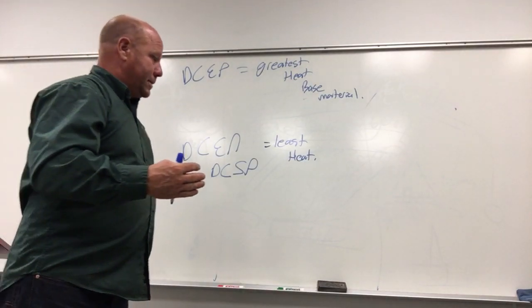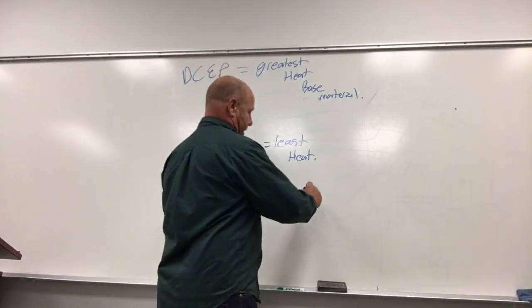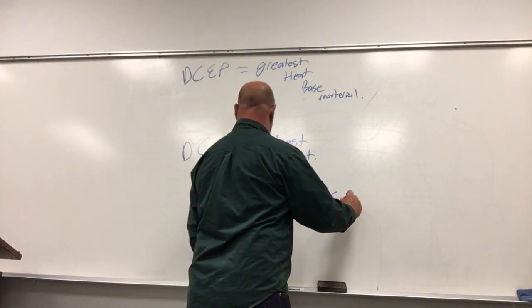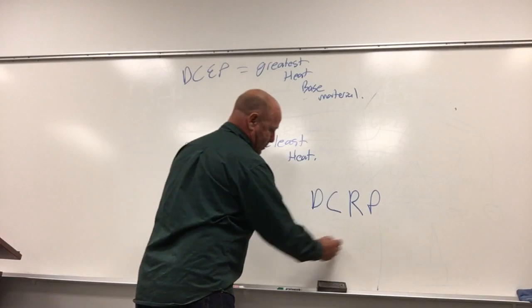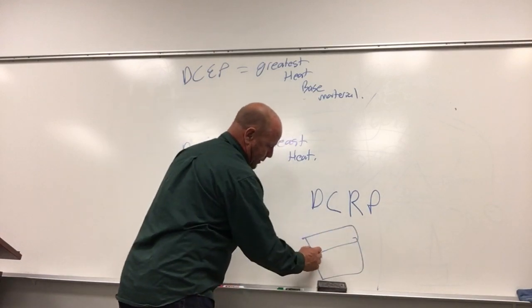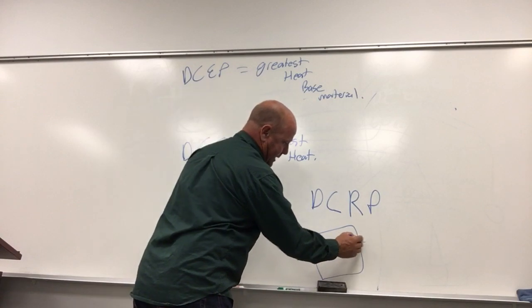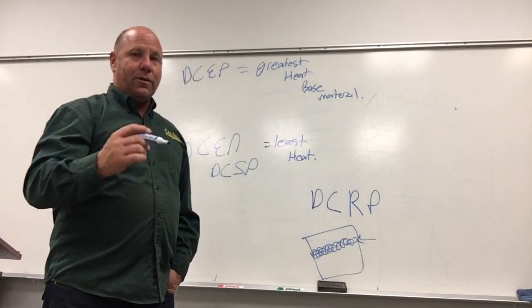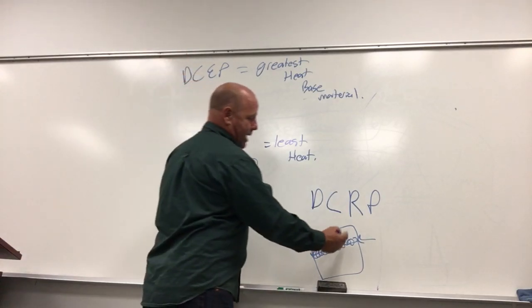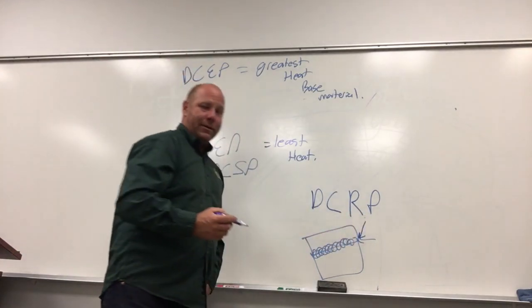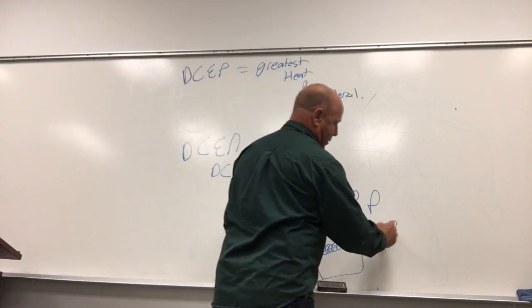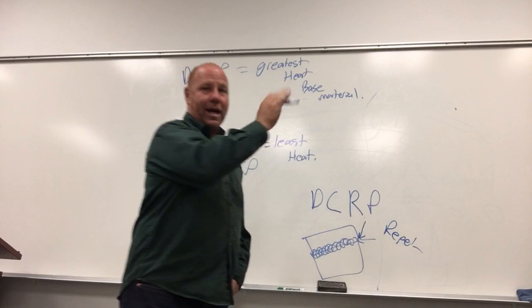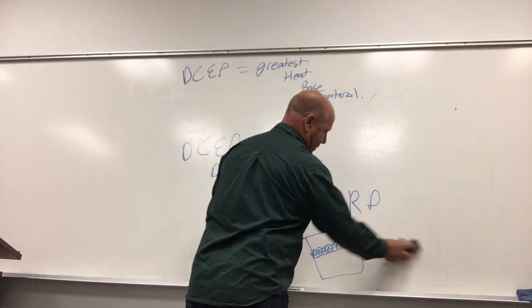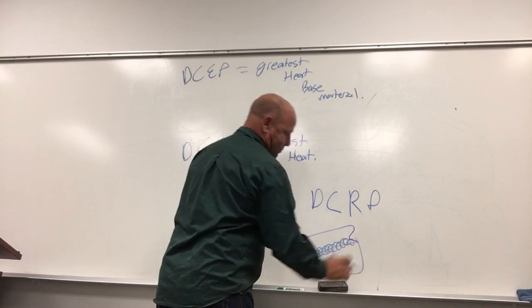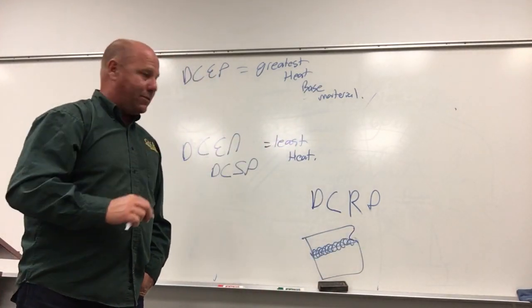Sometimes when you're welding with the DC process, actually every time, let's say you're doing a couple of plates and you're doing DC reverse polarity. Remember that's the same as electrode positive. You have two plates and you weld across. By the time you start reaching this end, you have magnetically charged these plates, and rather than attract this little ball into the puddle like we discussed before, you start to repel that ball. This ball goes flying out of the puddle over and over again. You actually repel it off, so that at the end of the plate, you end up with like a little divot like that, a little hole. Your weld is just a little flatter.